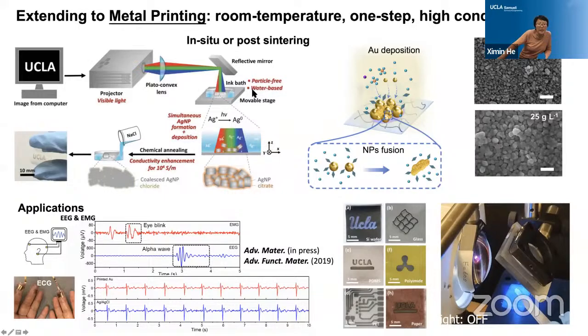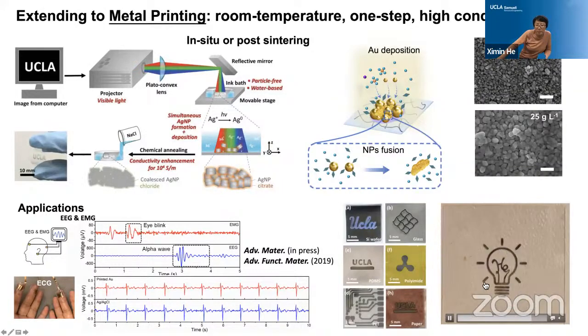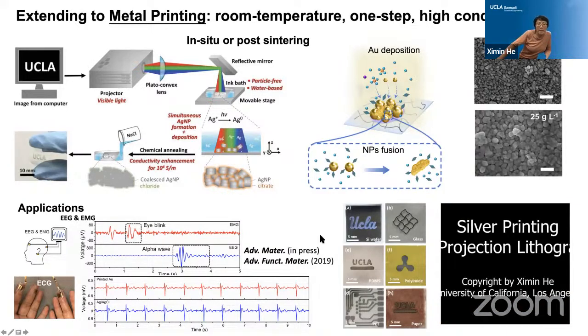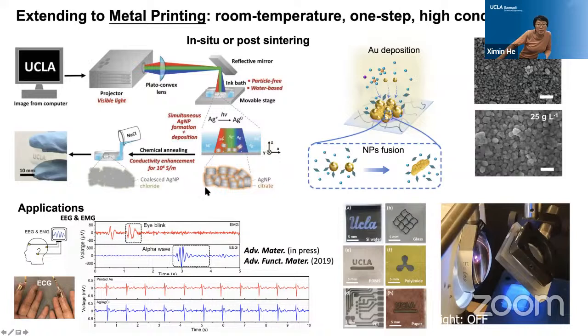In the case of silver, we did a quick rinsing with a table salt solution, and then it can instantly boost the conductivity by 4 orders of magnitude. So you can produce this silvery bright color, as you may see here. This black pattern after the salt rinsing becomes a light-colored silvery metal. And this also improves the connectivity.